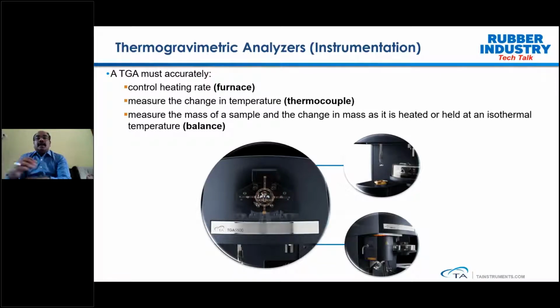Here, the balance is the heart of any TGA, because that's the one which is going to measure the change in weight. So these are the three major criteria. Before any selection of a TGA, you need to see how the furnace is going to control the heating temperature, and how accurately the thermocouples measure the temperature. So you need to see the temperature accuracy and resolution, and then comes the balance performance.